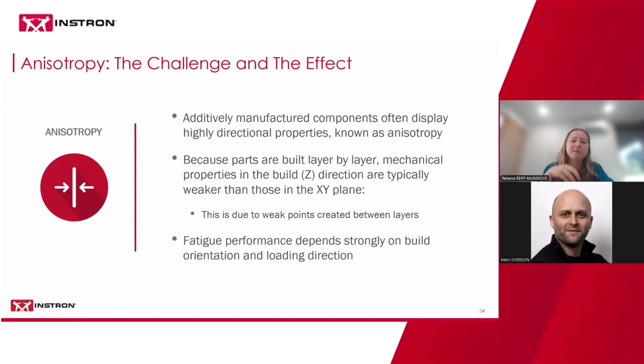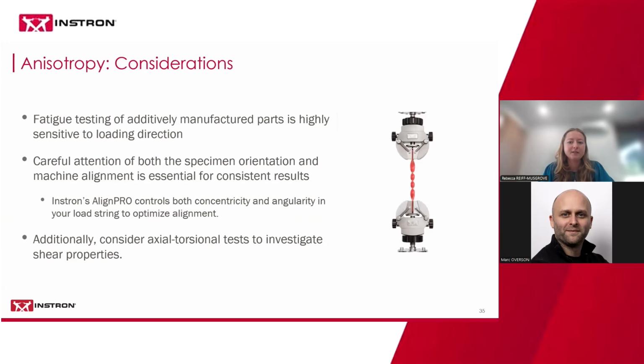And we generally see the build or Z direction is weaker due to those weak points created between layers. So the effect of that, and I just included it on the same slide here, is that fatigue performance does depend strongly on build orientation and the loading direction. Because fatigue testing is sensitive to loading direction, we need to pay careful attention to both the specimen orientation, so where it's been taken from in the build direction, and again, things like the specimen inputs, to make sure we're writing down where we're testing from, but also the machine alignment to make sure we get consistent results.